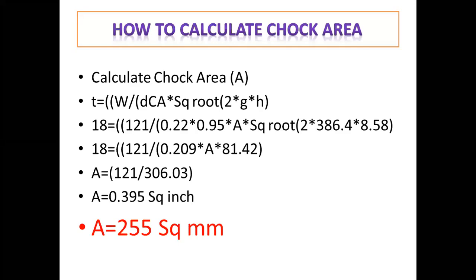Mind well, in cast iron, if you have a pouring temperature of 1380 or 1400 max, for a 60 kg or 80 kg casting, the choke area will be around 300 to 400 mm square, as a thumb rule. But this calculation of choke area is most important. As per choke area, if we do the runner bar and gating system, I give 100% guarantee that pouring time will be correct. There will not be any problem. We have to maintain the choke area correctly, and accordingly the runner and downsprue have to be calculated. If we do that, we'll get correct pouring time and there will not be blowholes.